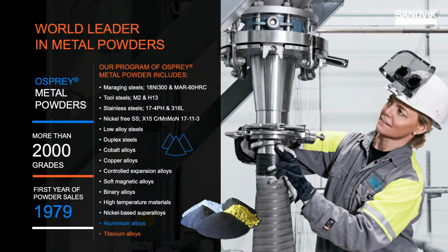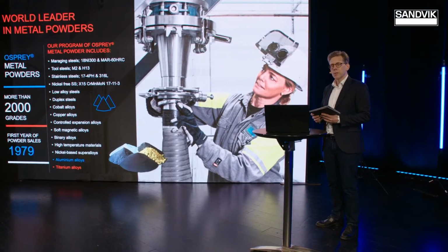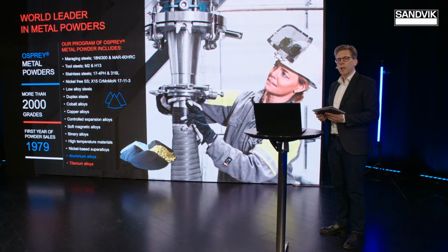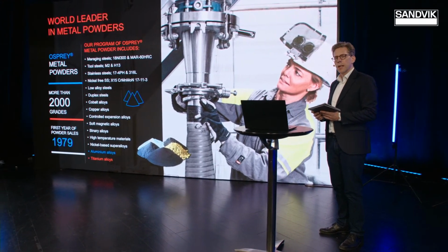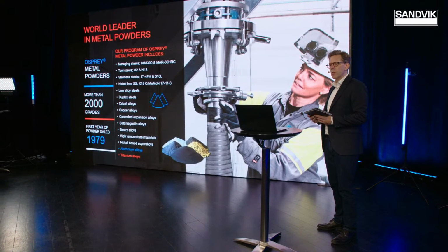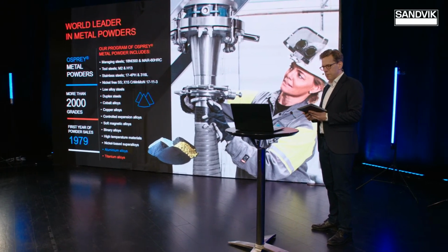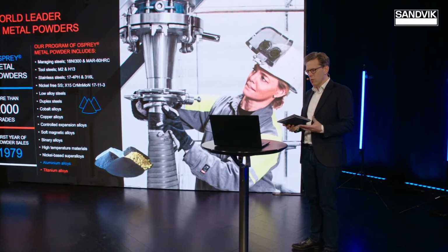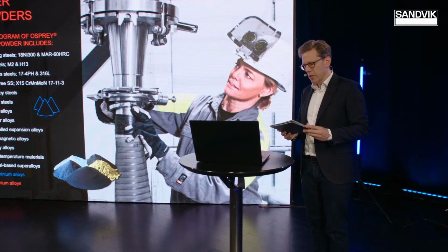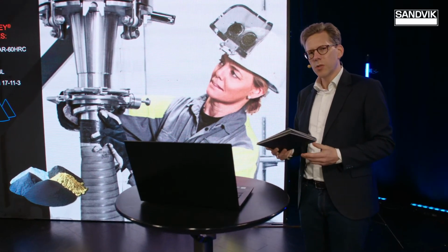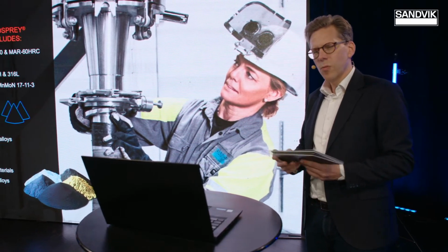Well, in the VIGA plant that we have, we do nickel-based superalloys mainly, but also some really complicated iron-based alloys, where it's of high interest to have a clean product, as clean as possible. And then in the EIGA plant, that we inaugurated last year, we atomize titanium 6 aluminium 4 vanadium as a start. We do 2 different grades. When it comes to powder characteristics, what about them, Paul? How do you characterize them?